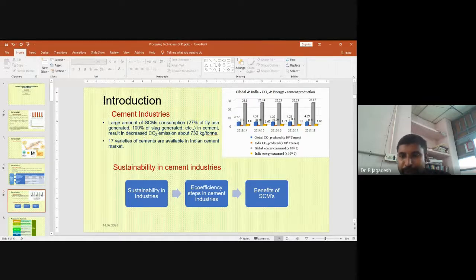If you see this picture on the right side, it indicates CO2 and energy consumption globally and in the Indian scenario. You can see it is rapidly increasing - CO2 emission going from 4.27 to 4.39 at global level, whereas in Indian scenario it increased from 0.3 to 0.31 into 10 power 9 tons CO2. Energy consumption increased from 26.1 to 26.87 in global scenario from 2013 to 2017, whereas in Indian scenario it increased from 1.8 to 1.86 into 10 power 12 joules.